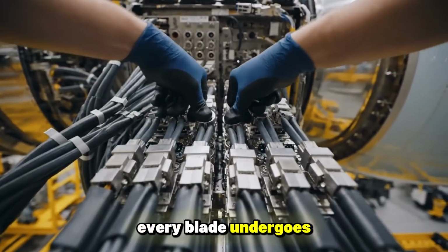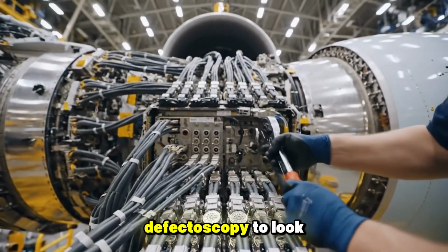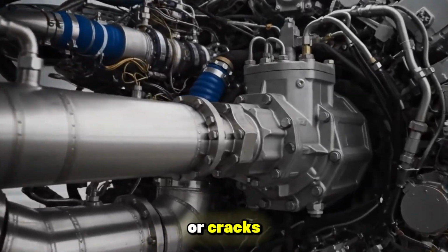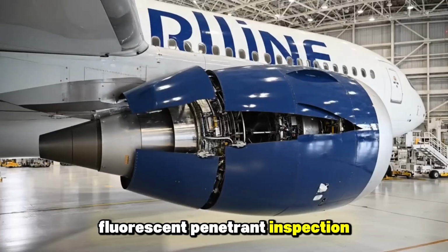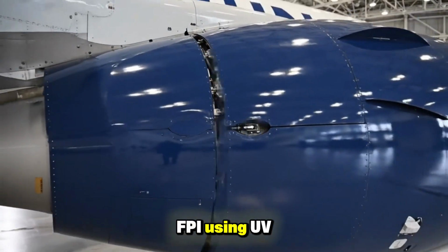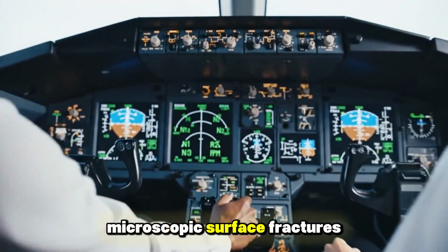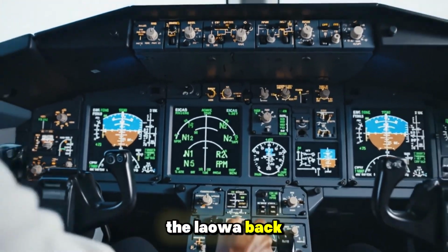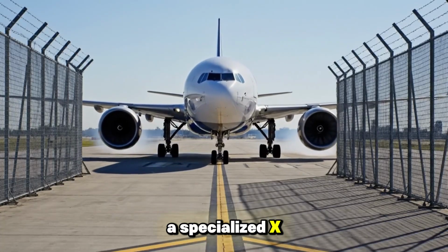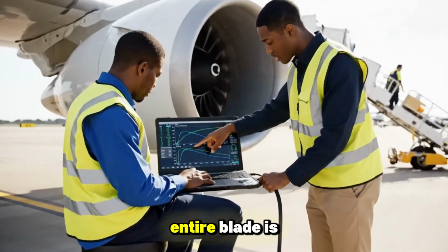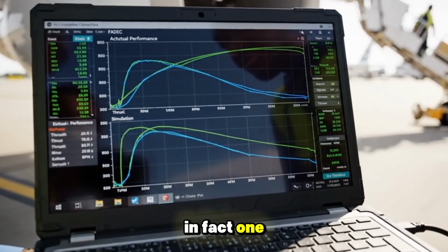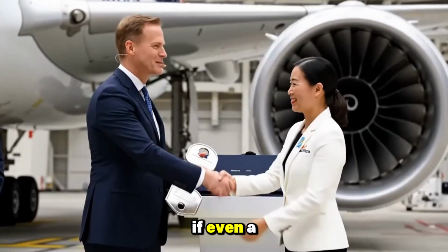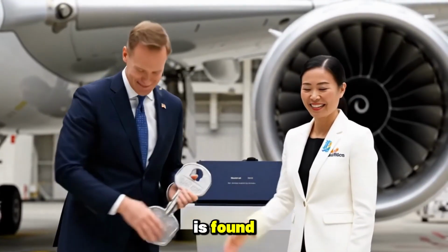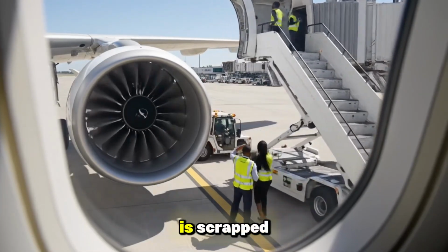Every blade undergoes X-ray defectoscopy to look for internal voids or cracks. Fluorescent penetrant inspection, FPI, using UV light to find microscopic surface fractures. Laue back reflection, a specialized X-ray technique to confirm that the entire blade is, in fact, one single crystal. If even a tiny secondary grain is found, the $15,000 blade is scrapped.